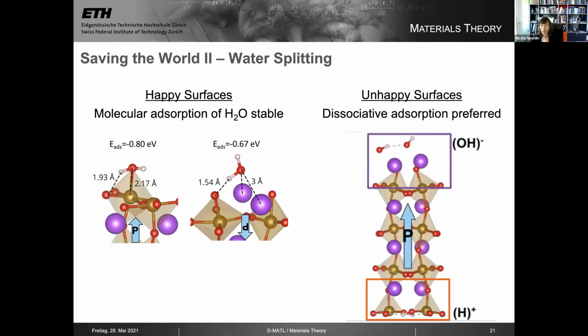On the unhappy surfaces, we still have adsorption. There's still a negative adsorption energy, but this time it's for the dissociated ions of water. And of course, the OH minus ions adsorb, oh, I've turned this around, I'm sorry, adsorb on the positive charge surface, which is the bismuth. I had that on the bottom before, I apologize for that. And the H plus ions adsorb on the negatively charged FeO2 surface.